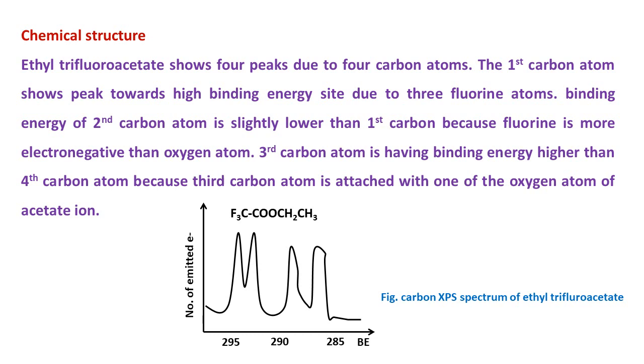Due to the three fluorine atoms, three fluorine atoms are attached to first carbon atom which is having higher binding energy. The binding energy of second carbon atom is slightly lower than first carbon atom because fluorine is more electronegative than oxygen atom. Third carbon atom is having binding energy higher than fourth carbon atom because third carbon atom is attached with one of the oxygen atoms of acetate ion. Therefore, binding energy decreases from first to fourth carbon atom.